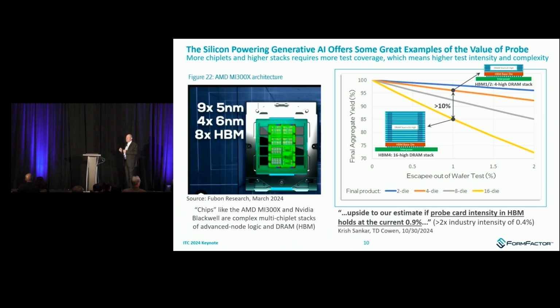If I go to a 16-high stack, however, the math gets pretty sobering, right? And this is the same 1% gap to KGD. And this is a real example, right? HBM4 under development right now by all the major DRAM manufacturers, being pushed very, very hard by customers like NVIDIA and AMD. If you think about just the implications of going to a 16-high stack versus a 4-high stack, everything else being equal, that drives a 10% yield gap for the final assembler, right? So that's one of the reasons why there's this push towards higher and higher test intensity at wafer probe to drive the escapes at wafer test down and get closer to known good die.